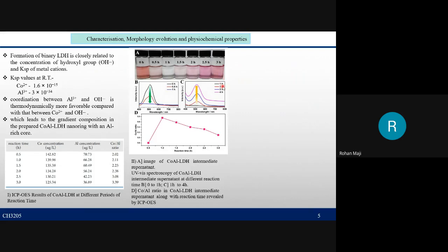If we analyze further with inductively coupled plasma optical emission spectrometry, that is ICP-OES data, here we can see that the cobalt 2+ to aluminum 3+ ratio increases in the solid sample with reaction time. This indicates that Al3+ cations are more favorable to coordinate with the OH- ions than cobalt 2+ at the early stage of urea hydrolysis.